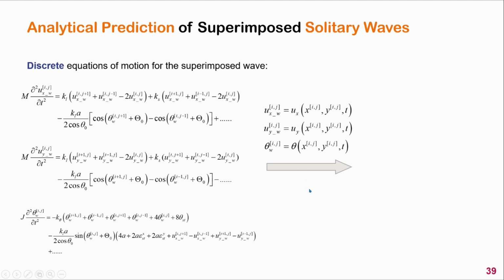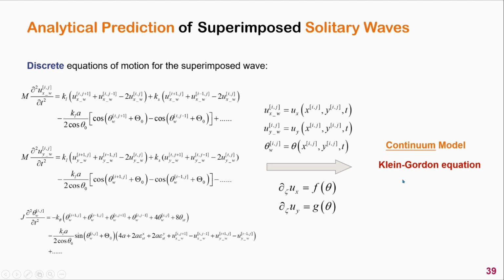Then we found that the two translational displacement components can be expressed using the rotational displacement component. Finally, we obtained the continuum model, the KG equation, which has a solitary solution depending on the coefficients C1, C2, C3. Okay, to examine the continuum model, we solve the initial discrete equation of motion directly using numerical tools in MATLAB.